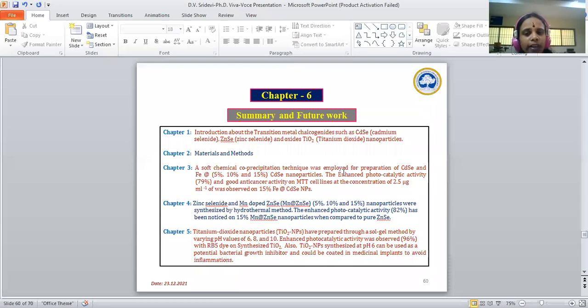In chapter 4, the zinc selenide and manganese-doped zinc selenide nanoparticles were synthesized by hydrothermal method. An enhanced photocatalytic activity of 82% was observed when 15% manganese was incorporated into the zinc selenide, noticed with 15% Mn in zinc selenide nanoparticles when compared to the pure zinc selenide.